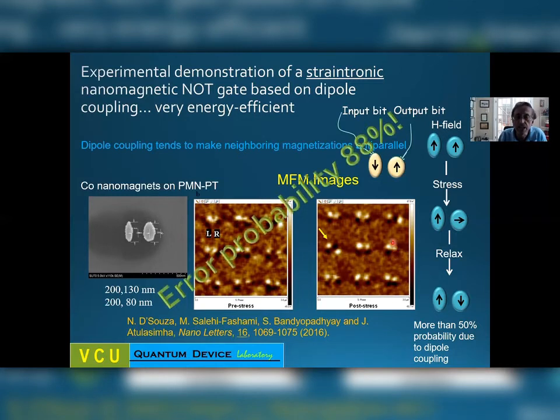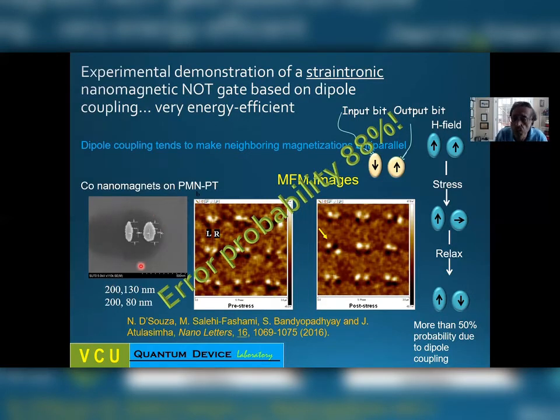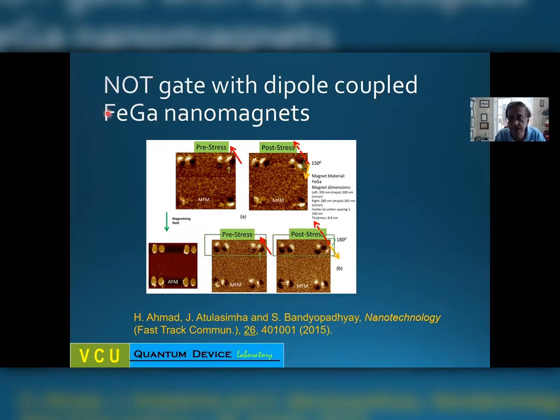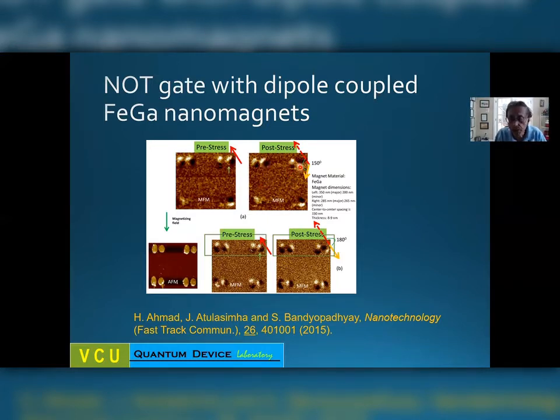We thought one reason for the high error was using cobalt nanomagnets, which are not very magnetostrictive — their magnetostriction is only about 60 parts per million. So we replaced cobalt with Galfenol (iron gallium), which has a magnetostriction of 300 ppm, five times higher than cobalt. We repeated the experiment and our statistics improved: now one out of four flipped, giving 25% success probability. Still not 50%, but the energy dissipation measured by CV² per pair is only about 3 to 4 attojoules — extremely low.